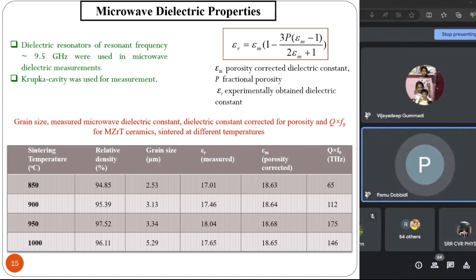These microwave measurements are also very tricky, and I don't want to go into the details now. If anybody is interested, we can discuss. We measured the properties at 9.5 gigahertz, and you see that we got an excellent dielectric constant of about 18. And for the quality factor, see what is reported in the literature. In the literature, it is reported in the gigahertz range. We got a very good response of about 175 terahertz. How did you get terahertz, you can ask. When you multiply the quality factor Q with the resonant frequency, that is 9.5 gigahertz, this is the number you get. This is the best number ever reported for this material, and that's where we are successful.